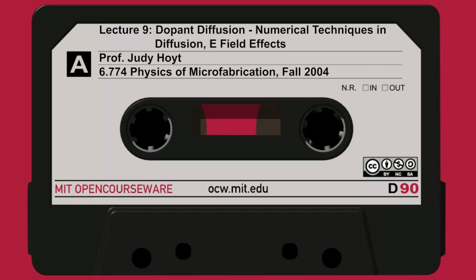And so you end up with this sort of hump and dip, which is a non-Fickian type of motion, but induced by the electric field created by the higher concentration arsenic species. So this can have quite a bit of an effect on the diffusion profiles near a junction, and we see this all the time in our devices.